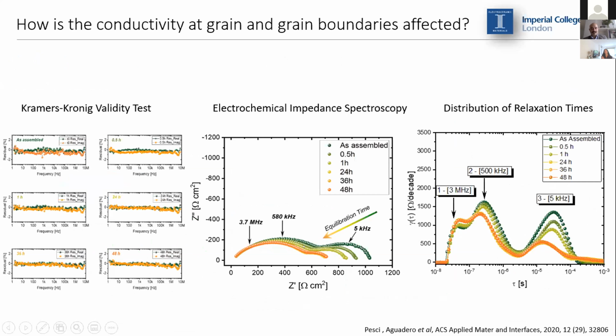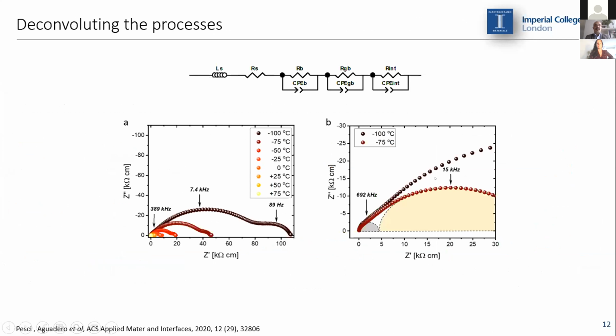So if you look at the orange impedance spectrum here, you can see that it appears to have only two semicircles, two features. But if we actually run distribution of relaxation time analysis, we see that we are looking at two processes occurring at the first semicircle. So DRT is very important in order to decide with how many circuits to fit our impedance data. As I said, at room temperature, it's very difficult to see the convolution of all the processes, but